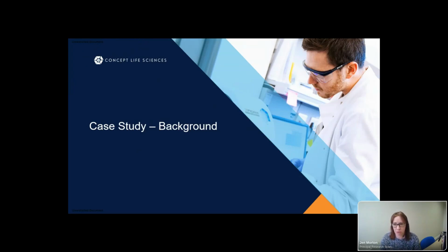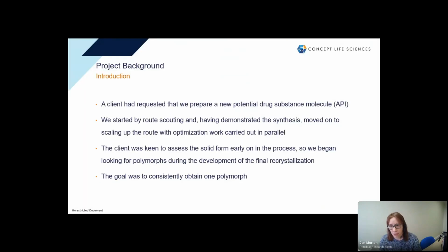Okay, moving on to the background then for our case study. As a CRO, most of the work we do is client work, and in this case, a client had requested that we prepare a potential new drug substance, active pharmaceutical ingredient. So we inherited a medicinal chemistry route for an analogue, and we started by route scouting around that. Having demonstrated the synthesis of the target molecule, we moved on to scaling up the route with optimization work being carried out in parallel, which is something that we often do for speed. The client was keen to assess the solid form early on in the process, so we began looking for polymorphs as we were starting to develop the final recrystallization. And the goal was to consistently obtain one polymorph.